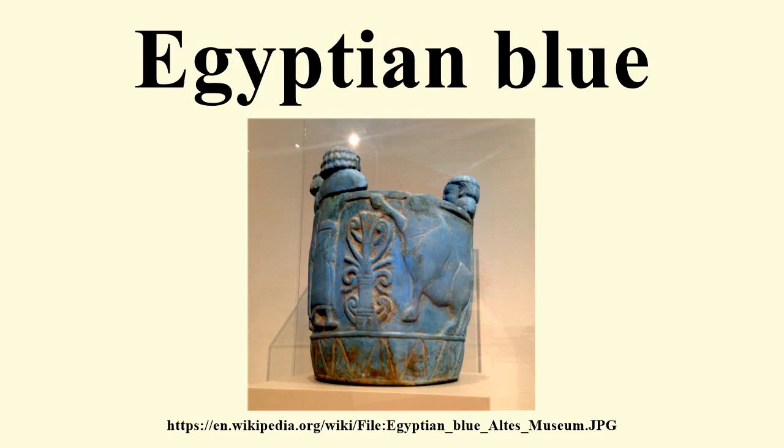Composition and manufacture. Several experiments have been carried out by scientists and archaeologists interested in analyzing the composition of Egyptian blue and the techniques used to manufacture it. It is now generally regarded as a multi-phase material that was produced by heating together quartz sand, a copper compound, calcium carbonate, and a small amount of an alkali at temperatures ranging between 800 and 1000 degrees Celsius for several hours. The result is cuprorivaite, or Egyptian blue, carbon dioxide, and water vapor. Cu2CO3(OH)2 + 8SiO2 + 2CaCO3 → 2CaCuSi4O10 + 3CO2 + H2O in its final state.